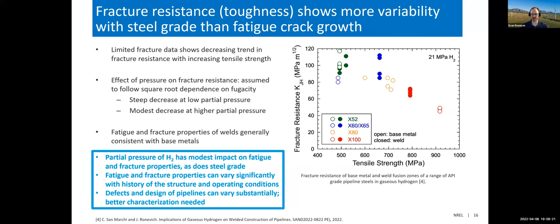higher strength steels tend to have more problems with hydrogen. We generally assume that the fracture resistance follows the square root dependence on fugacity. And so that means that there's a very steep decrease in fracture resistance as you add low amounts of hydrogen, get to a low partial pressure of hydrogen. But then as you increase hydrogen beyond that, it's more of a modest decrease. So once again, there's more of a significant impact going from no hydrogen to small amounts of hydrogen than from going from small amounts of hydrogen to large amounts.